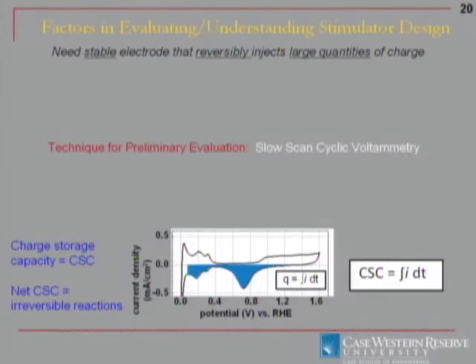But in the case of neural stimulation, evaluating these electrodes, what they do is to integrate the charge under the voltammogram, since charge is the integration of the current over time, and they define something called the charge storage capacity. And if the amount of charge in the cathodic direction is the same as the charge in the anodic direction, then the reversibility is high, which means nothing new is introduced into the electrolyte and thus into the tissue.